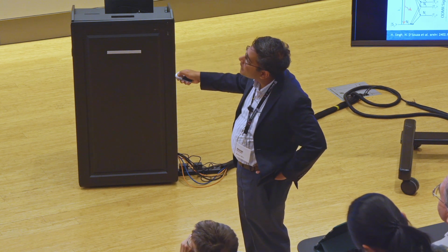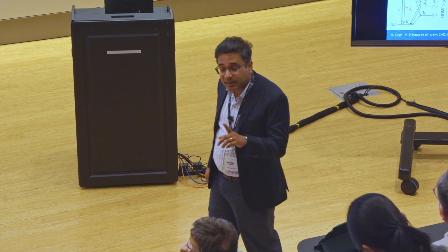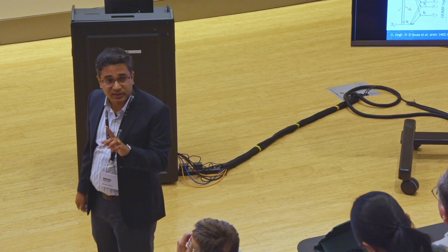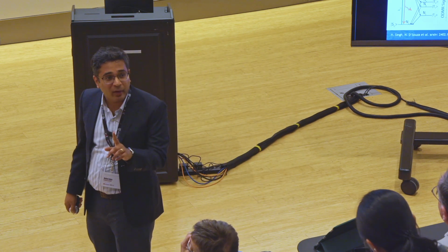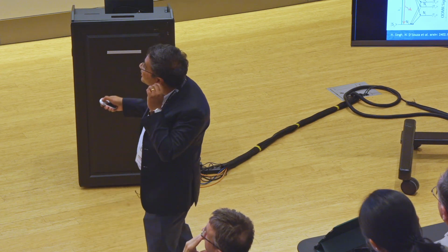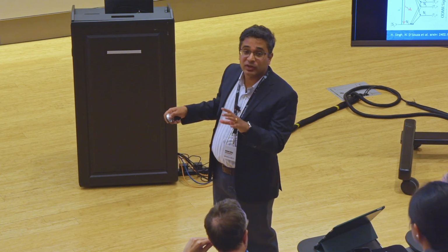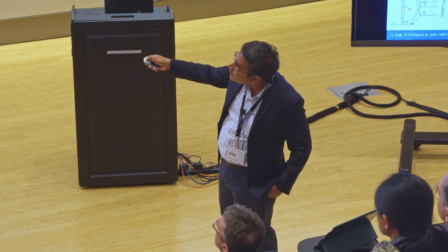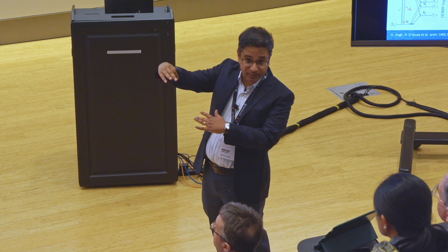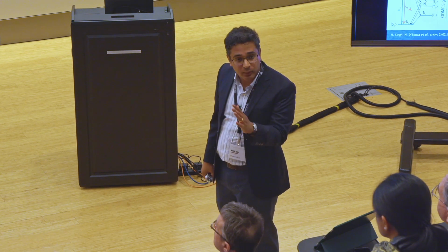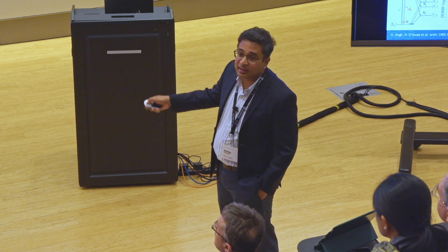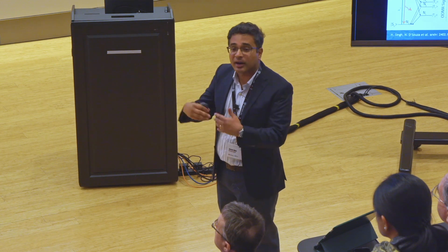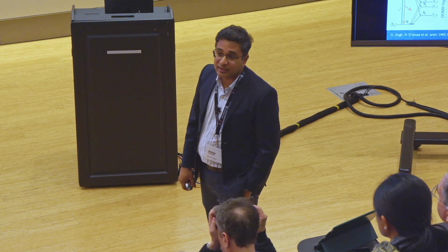And very importantly, because the ground state is a singlet, if you turn off the laser, the electron disappears. Okay, this is a very subtle point, but it has very high implications. So if you shine light, the electron is produced transiently, and the electron is produced in this triplet state, and that's what gets spin polarized. If you turn off the laser, or you wait a little bit of time, the electron goes in the singlet, it becomes diamagnetic, and as far as the nuclear spins are concerned, the electron disappears.